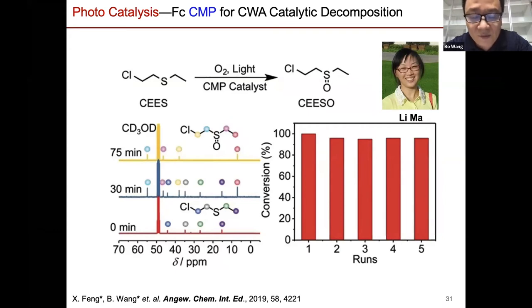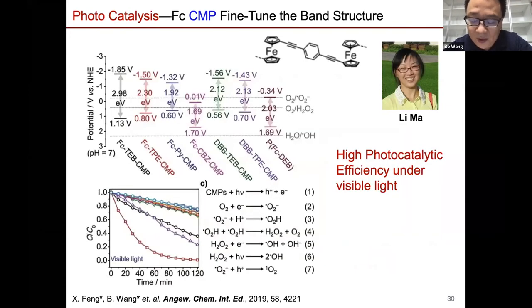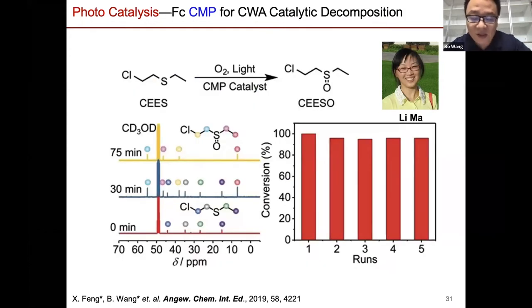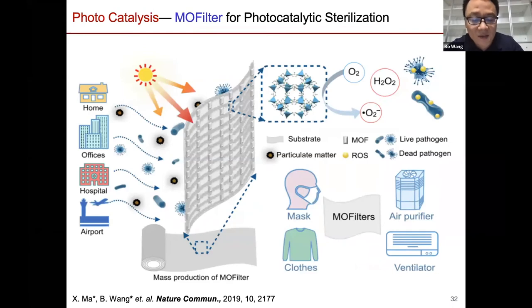And the structure by itself is highly stable. So when we coat it on the fabric, it can go across different runs, all the way up to 6-7 cycles. Of course, the performance or the speed is rather slow right now. You have to wait for 30 minutes all the way to 1 hour in order to decompose. Not as fast as the one introduced by Professor Farha, but we're trying to understand the band structure in those cases, and tune it in the way we want, eventually to decompose different types of pollutants or toxicants.